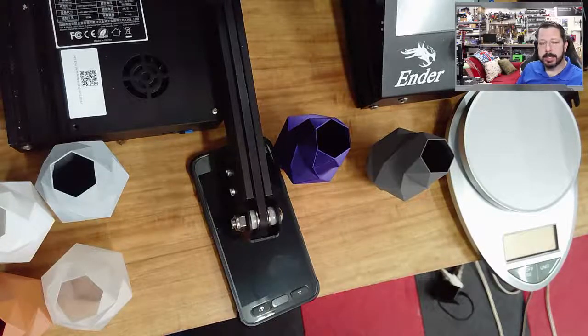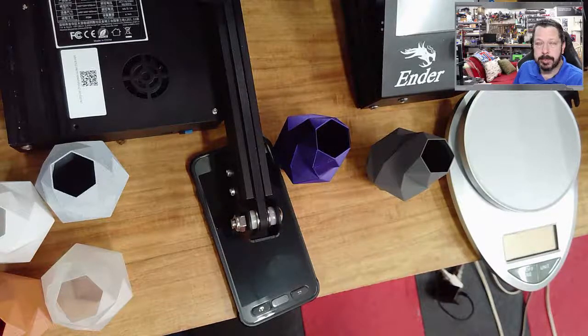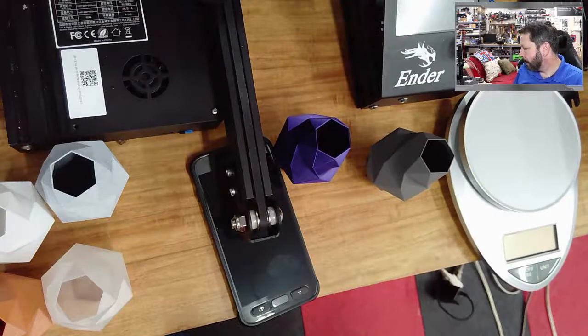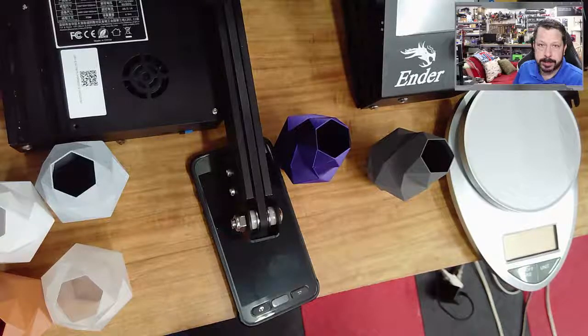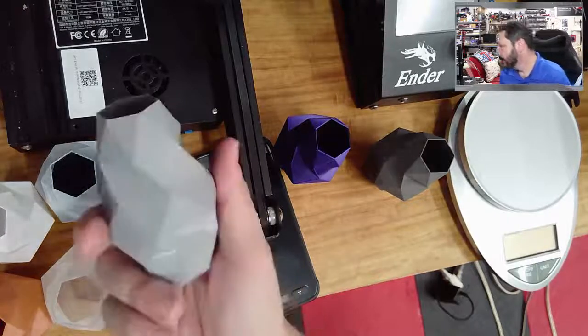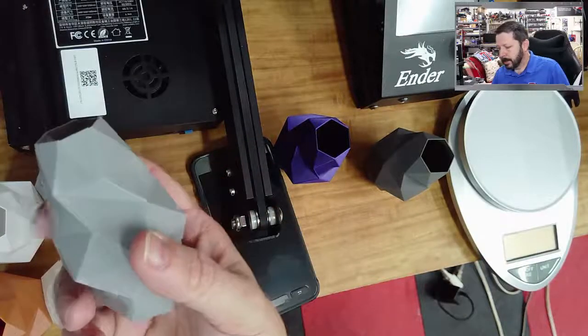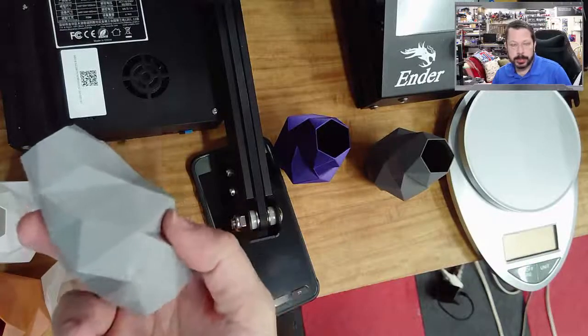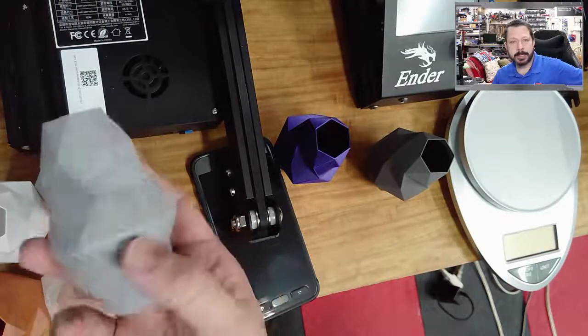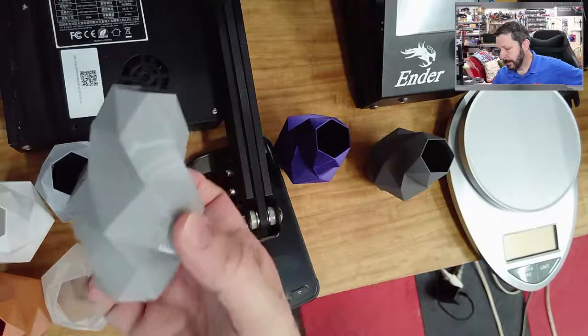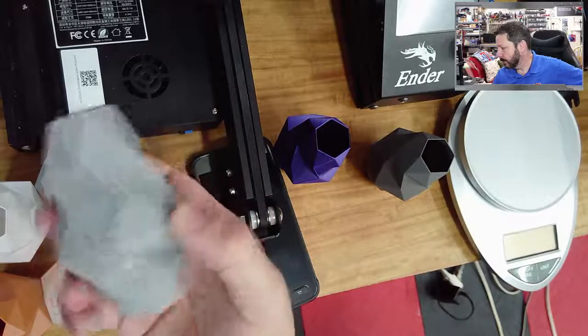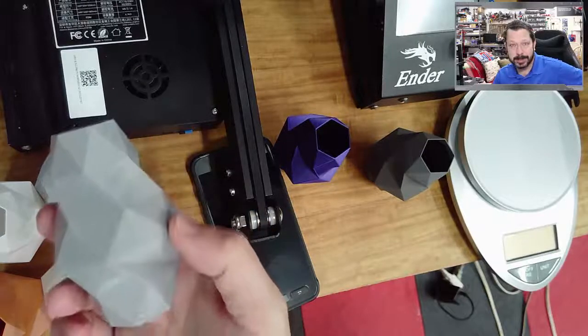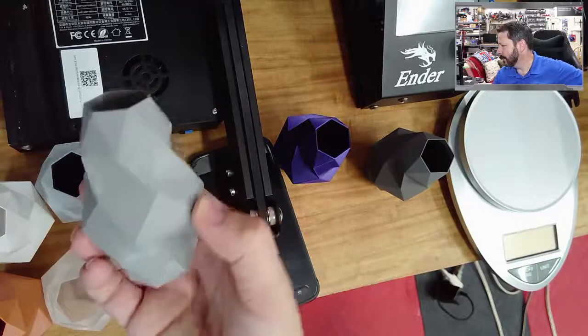That means that you can heat them 10 minutes or so at maybe 200-ish degrees Fahrenheit, not Celsius. And they will recrystallize. So they will become a little bit stronger, a little bit more heat resistant. So for instance, if I were to anneal this piece at 200 degrees Fahrenheit for 10 minutes or so, then instead of having a heat deflection, a glass transition temperature somewhere around 60 degrees Celsius, I'm mixing units there, but that's just what I'm doing.